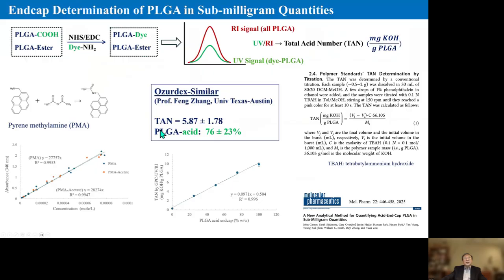Now, in this particular case, we modified the PLGA acid group using initially a fluorescent probe, but the fluorescent probe turns out to be not really fluorescent in organic solvent during GPC measurements. So after consultation with the FDA scientists, by the way, we published this particular approach already after we discussed with the great scientists at the FDA, upon suggestion by the FDA, we turned our attention to a UV probe because it isn't affected by the organic solvent.